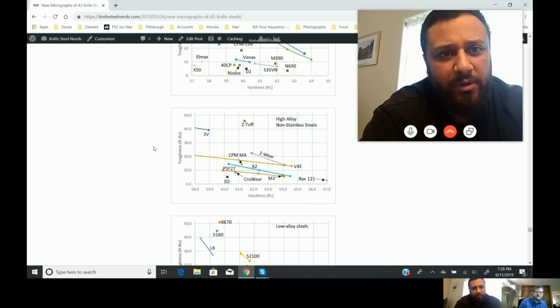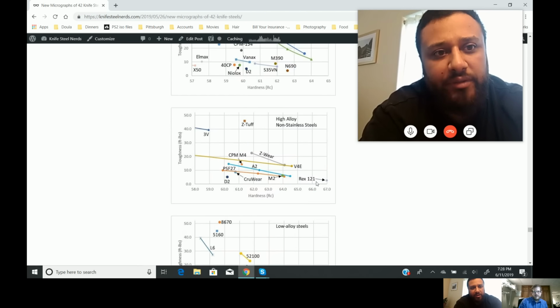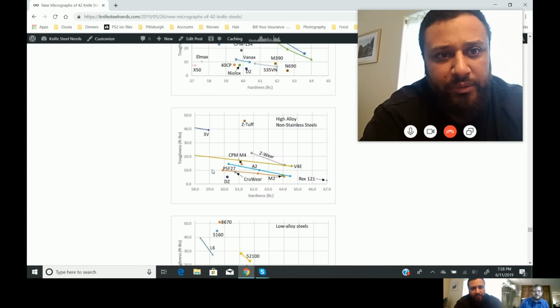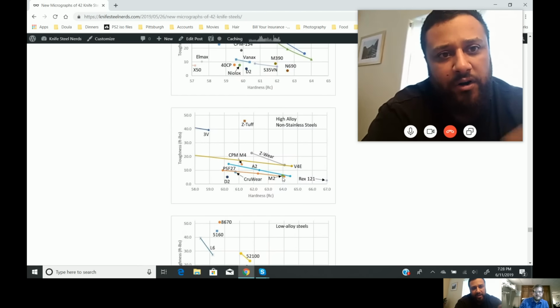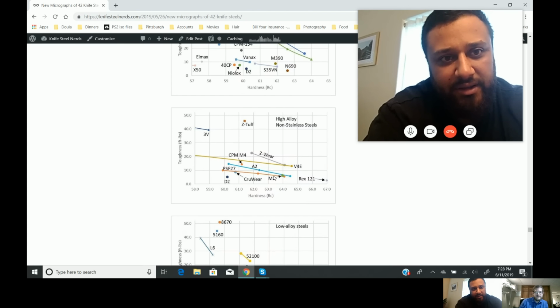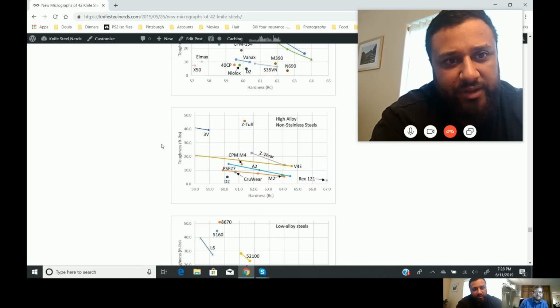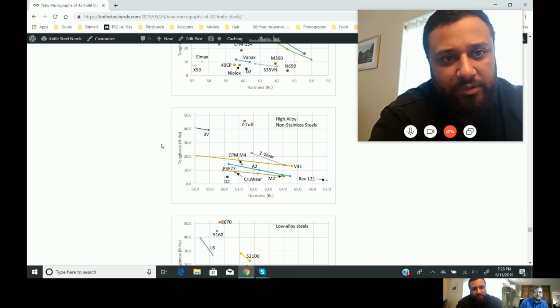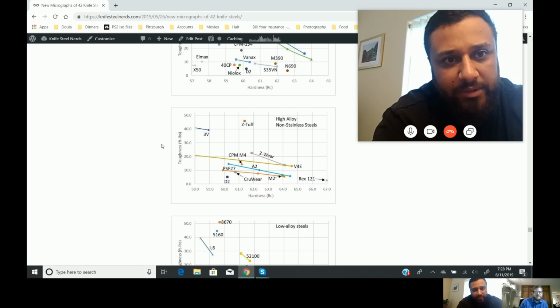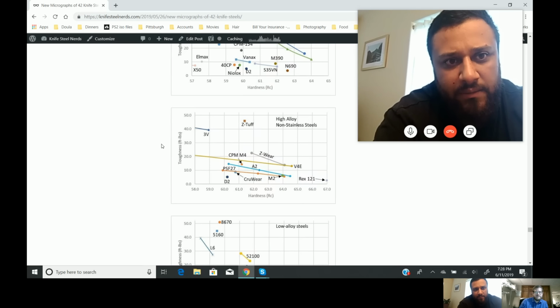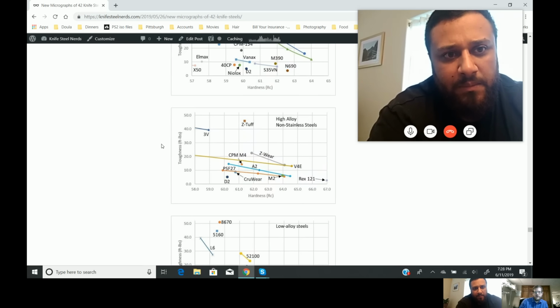And just real quick, we only tested one plot for M2, looked like. I'm looking at the PSF 27 line, and it looks like it blends right into the M2. So dang, that's actually surprising for how hard that M2 was. But then also the PSF 27, we saw that the carbides were a little bit larger than the M2, but they got about the same toughness at 64, huh? Look at that. Yeah, both do pretty well.